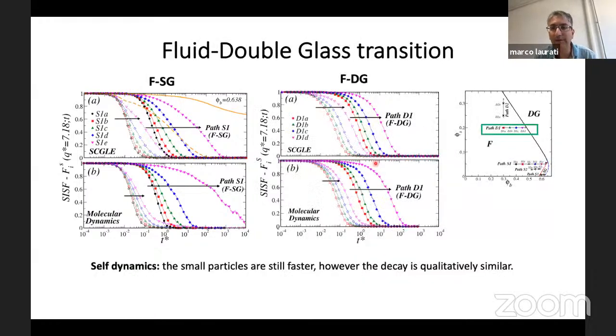So what happens then when we instead move to investigating the transition from the fluid to the double glass? Here I put again the previous transition as a reference. If you look now at the fluid to double glass, you can see clearly a very pronounced qualitative difference. Now you see that the slowdown of the dynamics while approaching the double glass transition is qualitatively very similar, also in the degree of slowdown between the small and the large particles in the self dynamics. Of course, the small particles are still faster than the large particles, but they slow down in a qualitatively similar way.